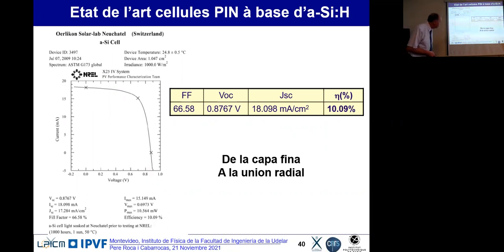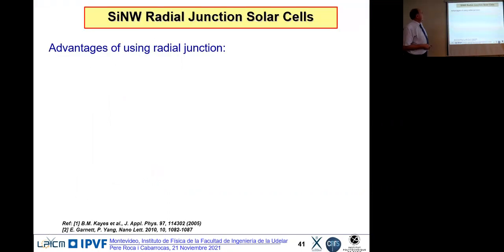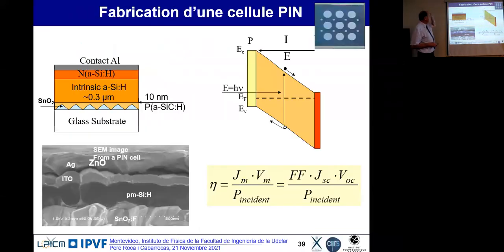So then we go. Here I can start from the thin films to radial junction. So now I will go to the last part, radial junctions, 5 minutes. How do you make a radial junction? Maybe why do you want to make a radial junction? If you make a thin film, and I want to have absorption, what should I do? Should I make the layer thicker? If I make the layer thicker, the electric field decreases, so I have less collection. So I have a trade-off between absorption and carrier collection.